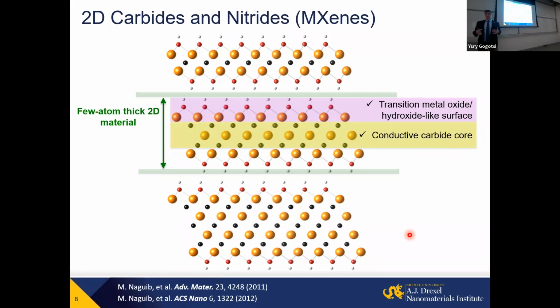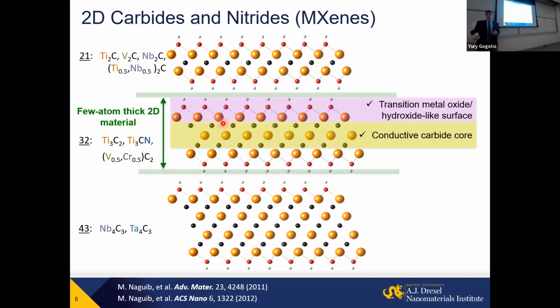There is something else. The metals have high density of states at the Fermi level, high concentration of carriers. By changing these atoms on the surface, especially when you go to the so-called 2-1 structure with 2 layers of transition metal, pulling electron density, you can open a band gap, or you can change basically the Fermi level. So what does it mean? You have metals, but they are tunable.